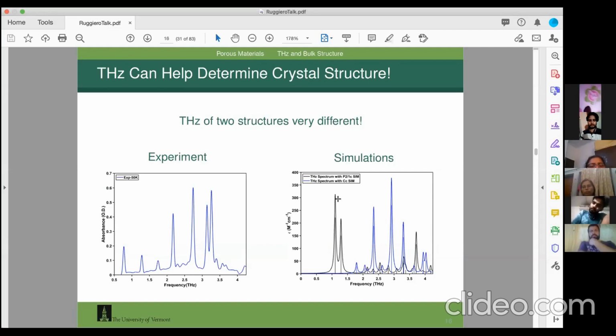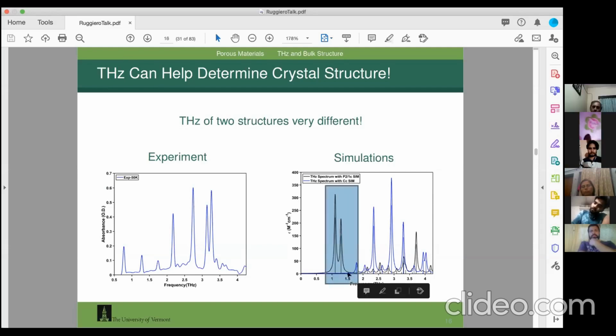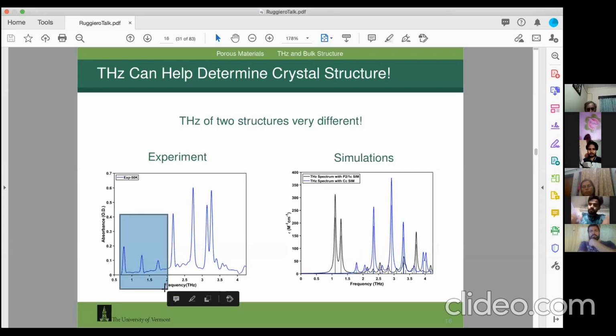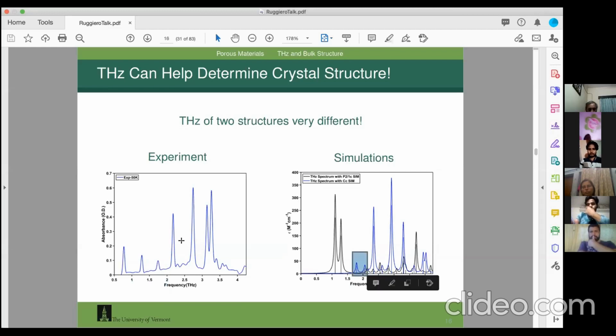And so that's what we see, where only the P21 on C, or the lower symmetry structure, predicts vibrations down here around 1.5 terahertz, which we see over here. We see some modes down here, where the CC space group doesn't predict anything until 1.7 terahertz, which starts about here.